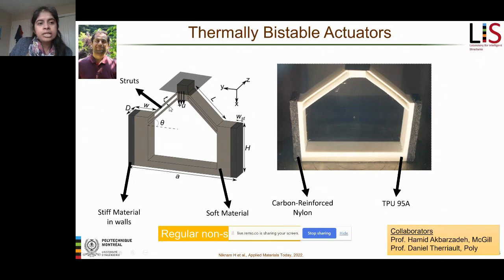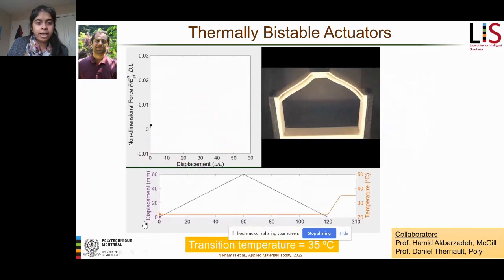So what we did was, by defining the dimensions of these lattice structures, here we can change the bistable characteristics of the material. So in this case, it's a normal commercial TPU that we bought, and then there is a commercial carbon fiber reinforced nylon. And by varying the size and width of this carbon fiber nylon, we can achieve the bistability or the actuation behavior in the structure. So I would like to show you a little video about that one.